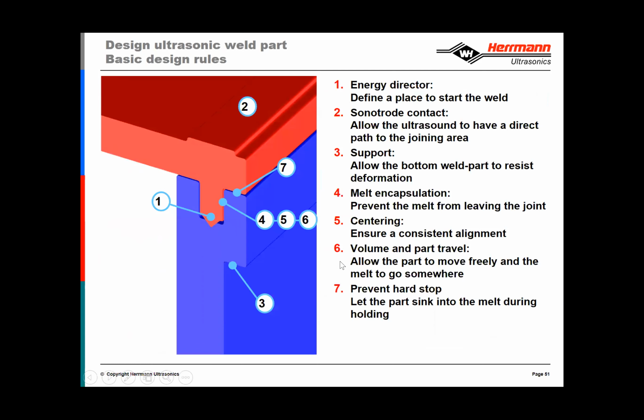Volume and part travel, allowing the part to move freely and the melt to go somewhere. So sometimes what we see is that parts are designed in a way that they press fit together, and this is not desirable. So there should be enough of a gap in between the parts here, such that if you did load them together and turn them upside down, they would fall apart.